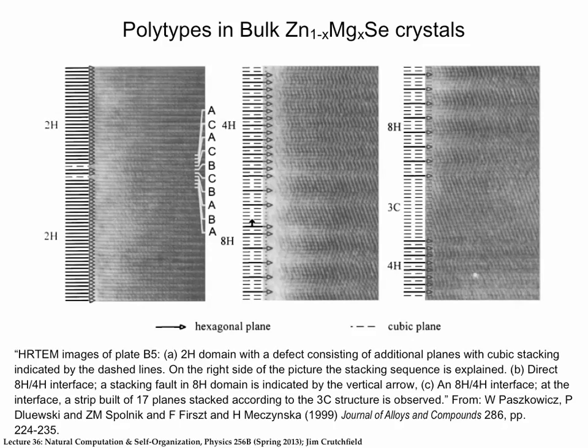It's something that no longer looks like there is a regular stacking pattern for this little guy here. You can see even longer period polytypes change. And in this one, we have just a direct change from the 8H, and the 8 means that this guy has a symmetry, a repeat distance of H, of 8. And let me just tell you what the 8H is. It wasn't on the previous slide. 8H is 1, 1, 1, 1, 4 ones, then 0, 0, 0, 0, 4 zeros.